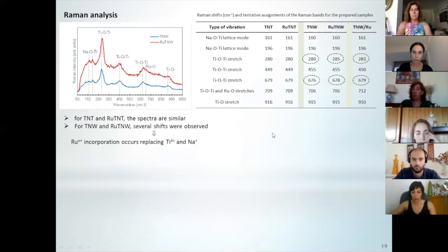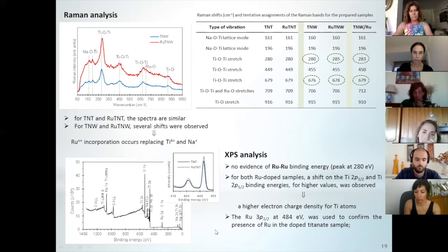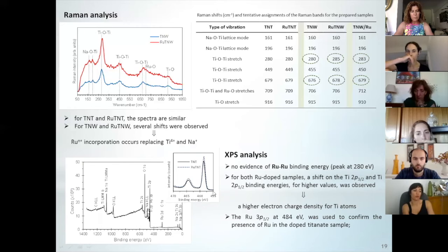Okay, so for titanate nanowires, we know that we have some ruthenium in the interlayers. We need to know where the ruthenium is in the nanotubes, because we know that we have ruthenium there. So we decided to do an XPS analysis, and what we can see here is that we have no ruthenium binding energy, so we have nothing with this kind of connection. We have a shift here in the peak of titanium. Sorry, it's missing here. This is titanium 2p. We have a shift in this peak, and this is telling us that we have some changes in the environment of titanium, and this is explained by some replacement of titanium by ruthenium.